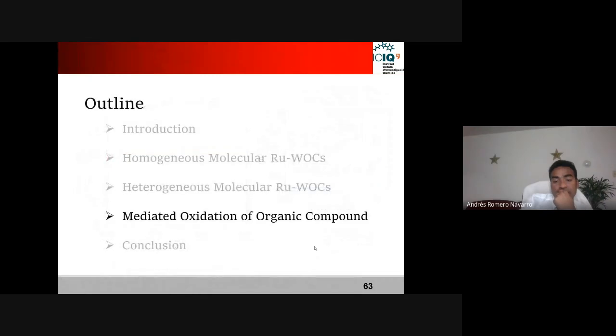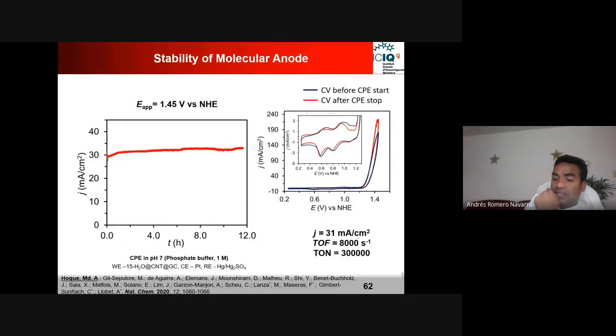One thing I wanted to say is that, as I mentioned in the introduction, our goal was that the current density has to be above 10 milliamp. And now we got a perfect system that shows even much higher, 3 times higher than the requirement of this current density. So it was a great breakthrough in our field, and that is why it was published in a very good journal called Nature Chemistry. That is one of the prominent journals in our scientific community. So yeah, that was my PhD work.